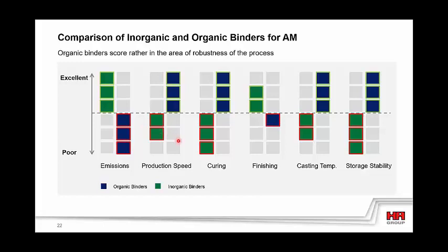On the curing side, in the furan process, the high reactivity leads to a fast self-curing and allows further handling without thermal post-curing. About 80% of the strength level is reached after 4 hours, and therefore post-treatment is not necessary. In the case of inorganics, the current state of the art requires thermal post-treatment, and this is done by post-drying in the microwave, as explained by Andy, prior to the removal from the job box. This intermediate step also influences the process time of the inorganics.